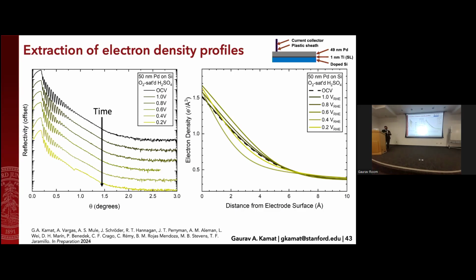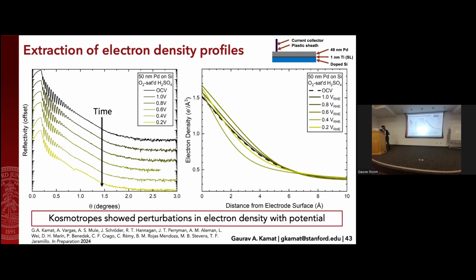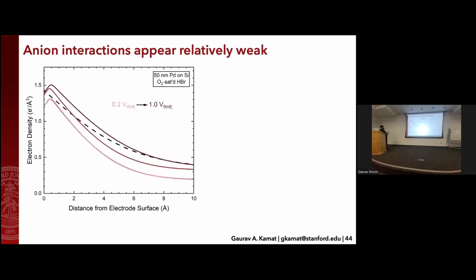And it's interesting because that's close to a point known as the potential of zero charge, when you have no overall charge that's built up at your surface. So it's very interesting that when we measure it, it's tightest to there, because it's very hard to confirm a lot of these measurements without doing additional theory calculations. So we saw here that cosmotropes have a lot of perturbations in electron density. This same data for perchlorate and for nitrate didn't really show large differences in charge or electron density. But in case of all the cosmotropes, you did see differences. And here's an example of one of those other differences. This is in hydrobromic acid, where you also see pretty large differences in the electron density.